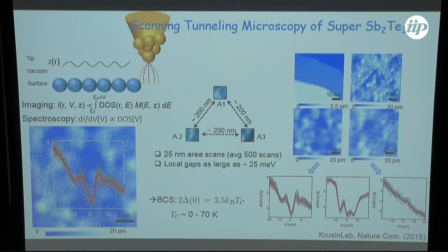Now the key was that these gaps were very sparse, in scans of 25 by 25 nanometers. They were about 100 to 200 nanometers apart, which is actually a pretty big job for STM to do.